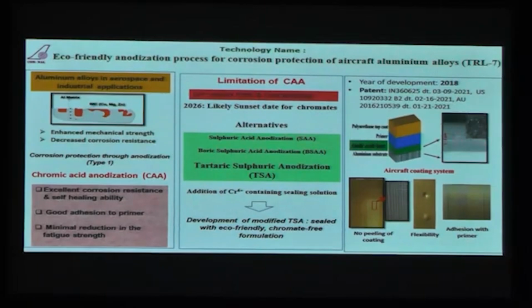For instance, in aerospace, the aluminum sheet is usually protected from corrosion by using an anodic layer, and on top of it we apply primer, and further the top coat. Chromic acid anodization is conventionally used because of its high corrosion protection, and it has very good adhesion to the primer, and it leads to minimal reduction in the fatigue strength.